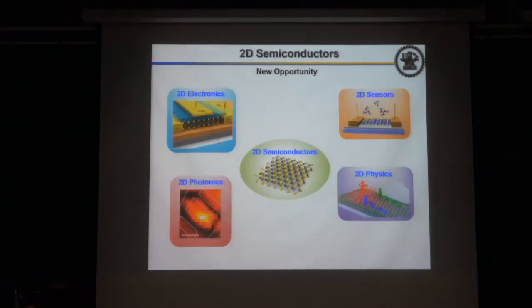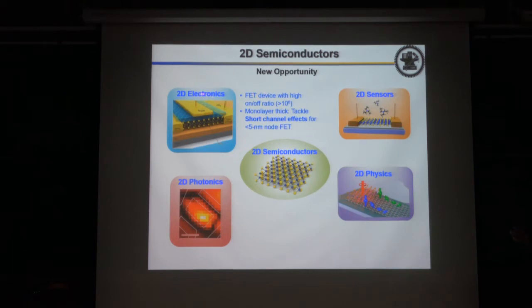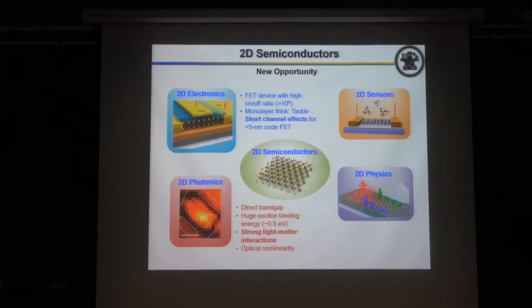Okay. So 2D semiconductors now have many new opportunities, like for 2D electronics, 2D photonics, 2D sensors, and also to explore some new physics in two-dimensional systems. The opportunity is that we can use this kind of semiconductor material to fabricate electronic devices with very high current on-off ratios, and maybe they can solve the short channel effect for 5-nanometer node technology. For photonics, this is a direct bandgap, and also has very large exciton binding energy, up to half an electron volt. In typical semiconductors, the binding energy is about a few milli-electron volts to a few tens of milli-electron volts. But in this case, it's half an electron volt. It's very huge. And also very strong light-matter interaction and very large optical nonlinearity.